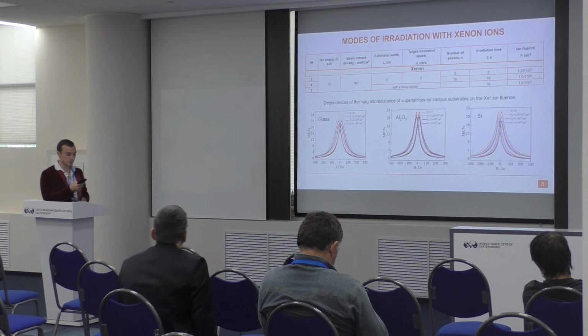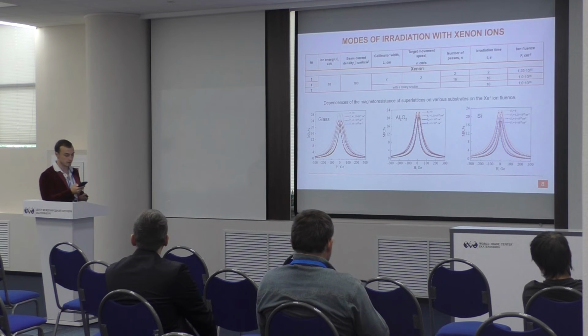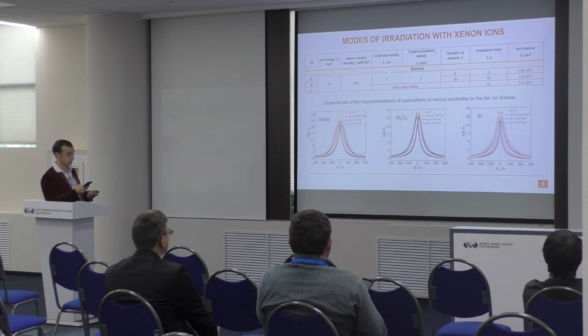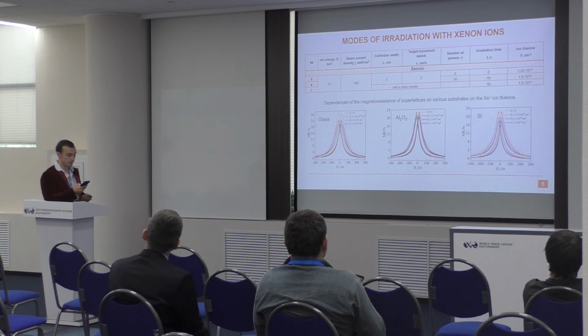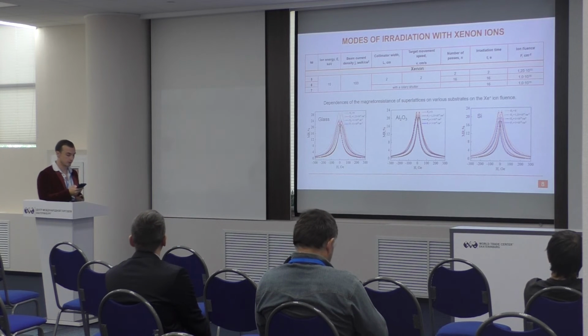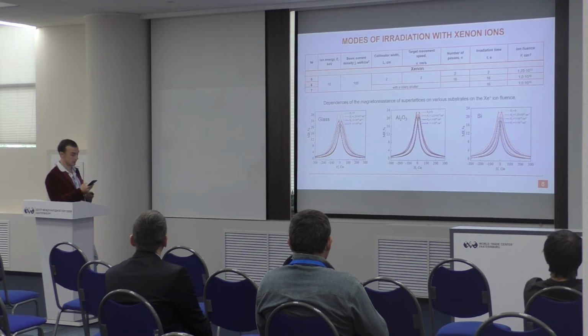This slide shows the modes of the irradiation with xenon ions. They are similar to argon ions. As a result of the obtained measurements, the irradiation of cobalt, iron, copper superlattices with xenon ions also leads to a decrease in their magnetoresistance for all three types of substrate.